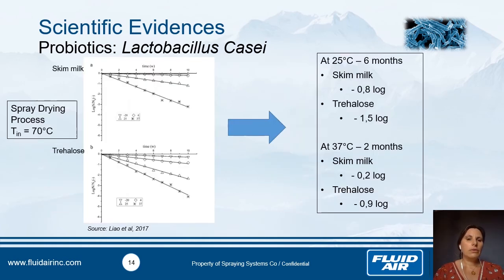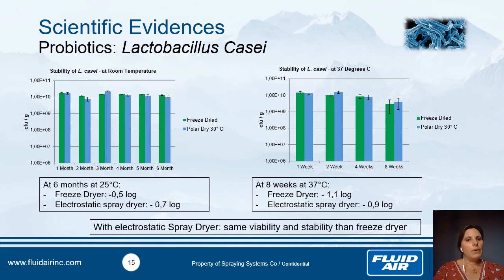We did exactly the same study with Lactobacillus casei and with the spray dryer. In this case, it was the inlet temperature at 70 degrees C, and so that means the outlet was between 30-40 degrees C, I think. And we observe after 6 months with trehalose a loss of 1.5, and at 37 degrees C after 2 months a loss of 0.9 log. When you can see the curve, we can say the stability is the same for freeze drying and electrostatic spray dryer. We are really close in the case of 8 weeks with the spray dryer, but a little bit higher. A little bit higher than a spray dryer in case of 6 months.